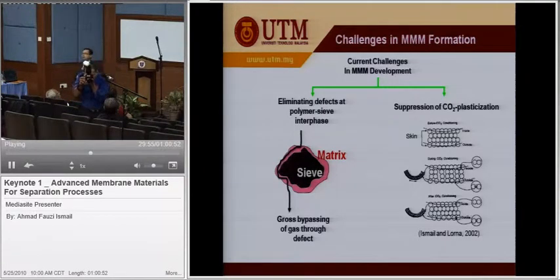However, because of the forced marriage between the polymer and the inorganic material, there are a lot of challenges. I don't like you, you don't like me. What happened? When you marry these two, there is always some form of defects that occur. And this defect is called the sieve-in-a-cage phenomenon.